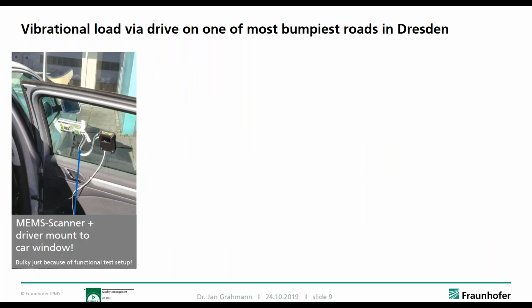Well, here I cannot say that by heart. It would be good if I have a few parameters, for example, sent after the webinar, so that I can give you a more qualified answer. The influence on the dynamic deformation is correlated to about the diameter of the mirror, which you gave me, 5mm, to the power of 5. The frequency goes in strongly to the power of 2, and the deflection angle goes in to the power of 1, so linearly. I would need to see these parameters all together in order to tell you where the dynamic deformation for our technology will probably be.